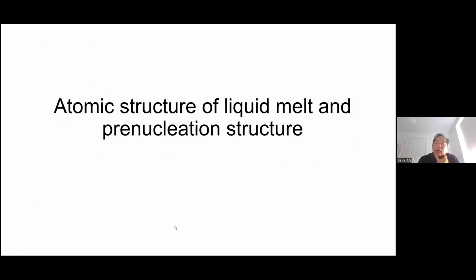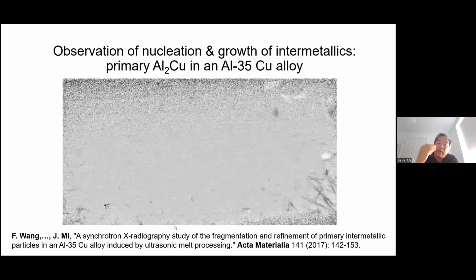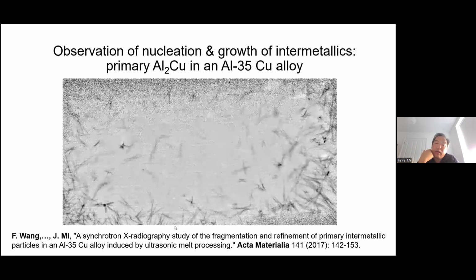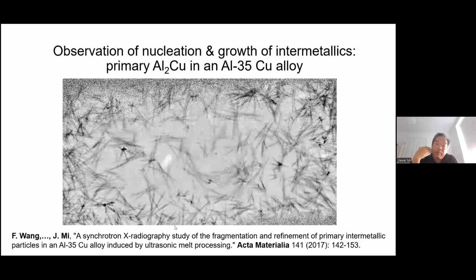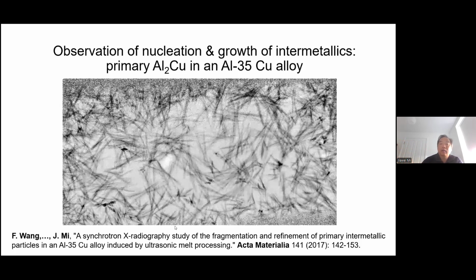So let's take a look at the atomic structure of a molten melt, and how, when you're cooling down, the atomic structure changes and evolves and leads to the nucleation of different types of crystalline phases or intermetallic phases. From an X-ray radiography point of view, if you have the correct X-ray, with sufficient penetration power and sufficient flux, it's quite easy to look at the structure of liquid materials.